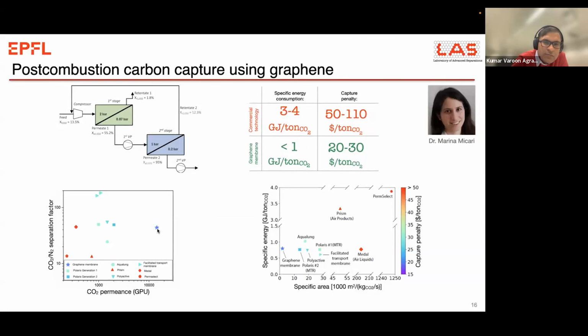Of course, these membranes that we are developing at EPFL are much better in terms of the gas permeance than many industrial and state-of-the-art work that has been shown. The selectivity that we show here is about 50, which is already quite good to design a membrane process to achieve a purity of 95%. If you take this kind of membrane and look at the specific energy, specific area and capture penalty with respect to all other state-of-the-art membrane technology, we can show that this becomes really attractive. In particular, the specific area, which is essentially the footprint of this membrane, can be quite low compared to what is out there, which makes it very attractive, especially when the footprint is a challenge.